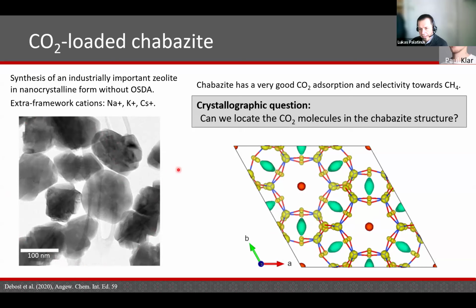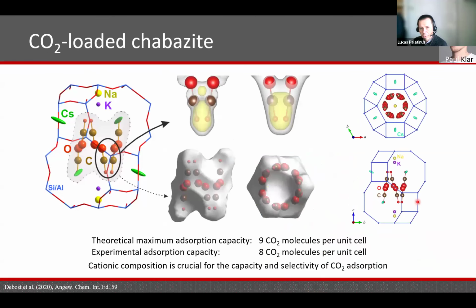So we measured the crystals with electron diffraction. This is the crystal structure solution. These yellow blobs here represent the framework atoms. This was straightforward, but also nothing new. The structure was known. But then looking in the cavity, we were indeed able to see the difference potential corresponding to the CO2 molecules. It was clear that one of the ends of the CO2 molecule is relatively strongly bound to the cation sitting here in the cage. But it was not really possible to determine the position of the molecule.